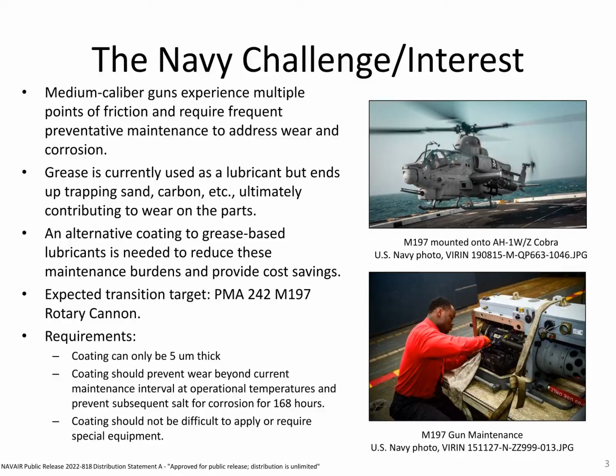Additionally, some of the challenges that the Navy has given us is that the coating should prevent wear beyond the current maintenance interval, which is every 15,000 rounds. And after withstanding 15,000 rounds of wear, the coating should be able to withstand 7 days in a salt fog chamber, which is the standard test that's used to assess corrosion. It's basically a fog chamber that circulates warm, salty water around and can induce corrosion on unprotected metals.